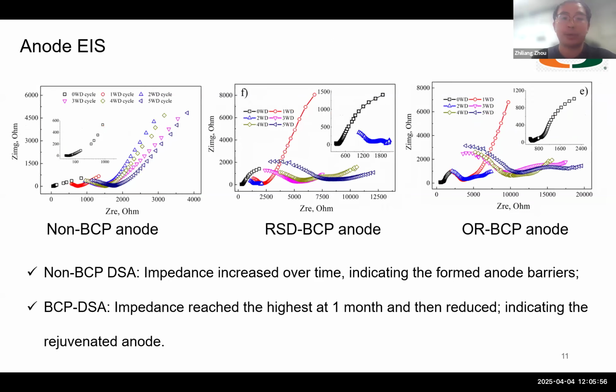This point is also proved through the EIS measurements, which can indicate the surface resistance of the sacrificial anodes. We can see from these results, the surface resistance of anodes without biochar increased over time. This can suggest the gradually formed solid state barriers on the surfaces of sacrificial anodes. However, for the sacrificial anodes with the biochar addition, their surface resistance values increased initially, but significantly decreased during the long term. And this can indicate the electrolyte buffering ability of the biochars.